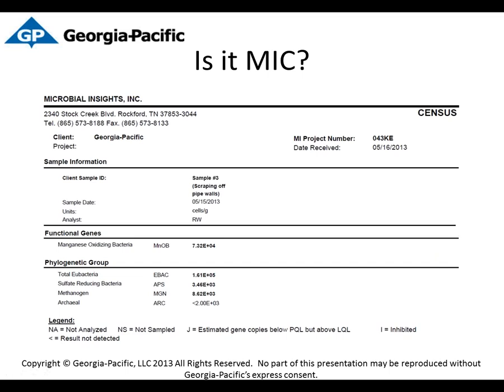or not. And being fortunate enough to have several veterans in our company, or veterans of the company, I should say, working there, that have been there 20, 30 years, this site in particular had a history of poor water quality, a lot of high manganese in the water. And to have high manganese in the water, it doesn't take but about 20 parts per billion, 30 parts per billion, and they consider that pretty high for manganese. So we knew we had high manganese in the history, but we thought we remedied the problem.